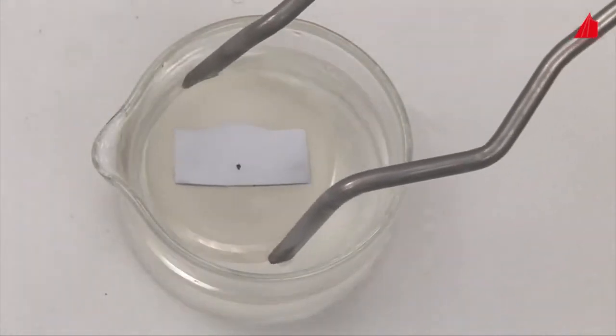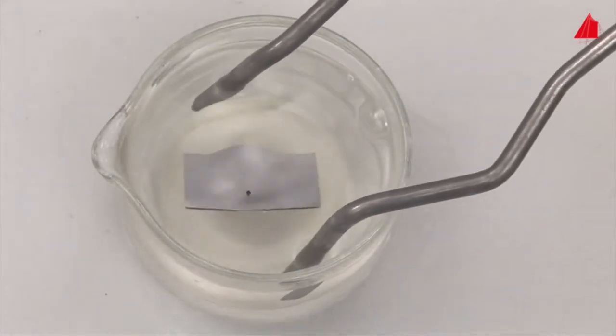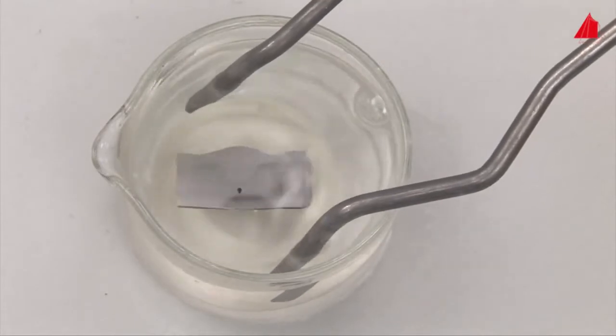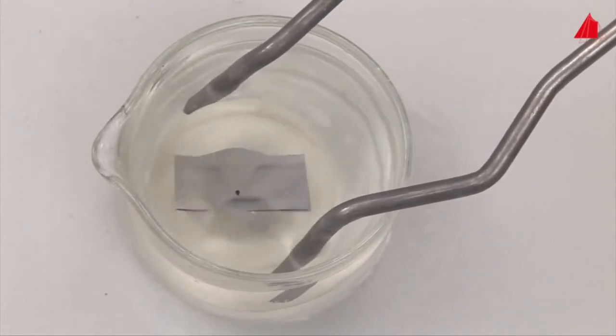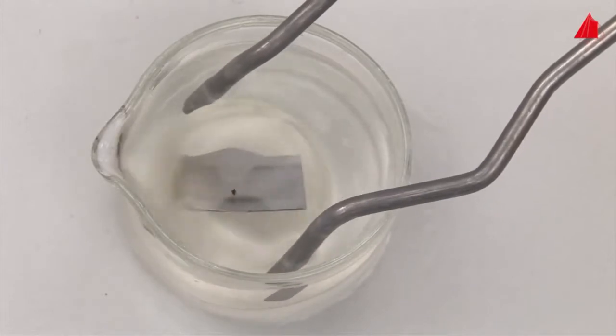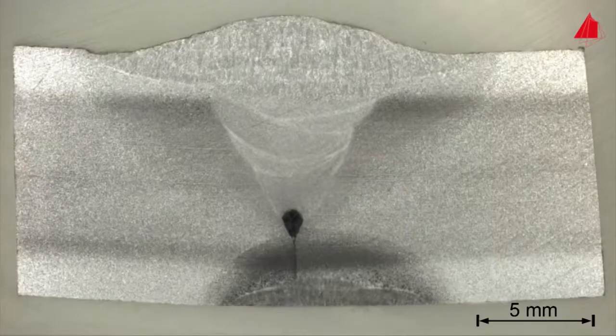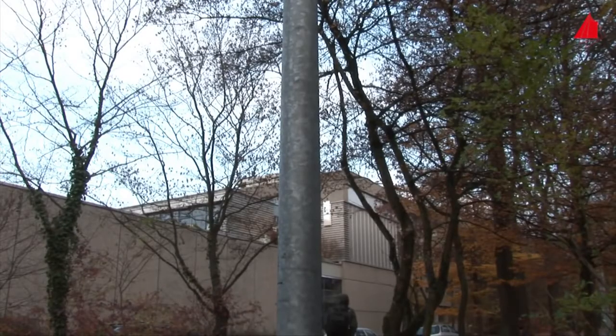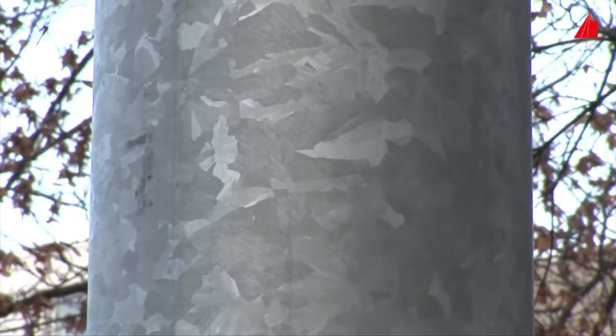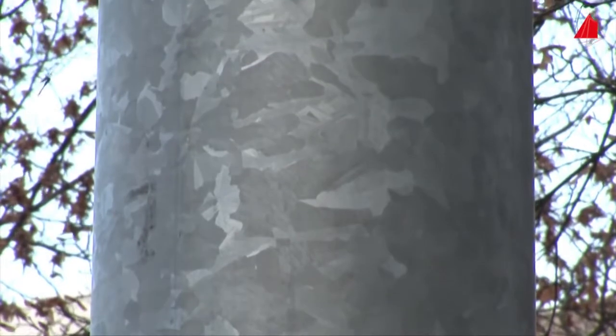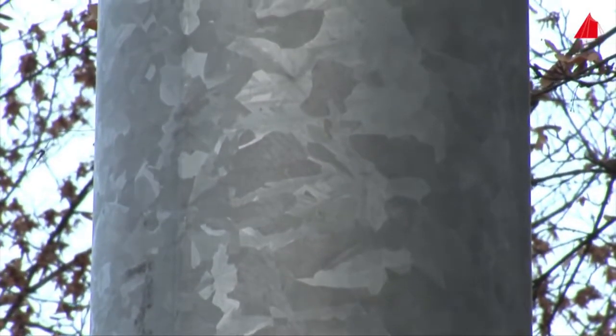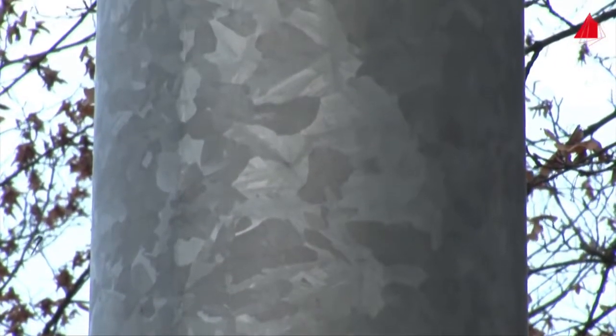Weld joints can also be examined metallographically. In our case, the etching process takes a little more time and the analysis is more difficult. But by and by, the structure inside the steel plates, the position of the weld passes, and the heat-affected zones may be identified with a skilled eye. Even in everyday life, one meets metallography. At this hot-dip galvanized lamppost, the rainwater has acted as an etchant over the years. The large flat zinc crystals have been structured on the surface and can be recognized as so-called spangle.